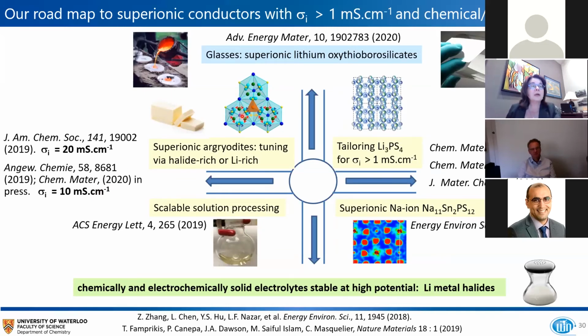We've also tuned the argyrodite structure by stuffing it with lithium, taking advantage of what we learned with the Li3PS4, and achieve conductivities upwards of 20 millisiemens per centimeter because of the beauty of this structure. And as I said, I'll be describing that in the next slide. So along with tailoring lithium thiophosphate, we've also managed to make materials by scalable solution processing methods. And we've also developed superionic materials as shown here, which also display this paddle wheel effect. And more recently, we've been working on electrolytes that are stable at high potential.